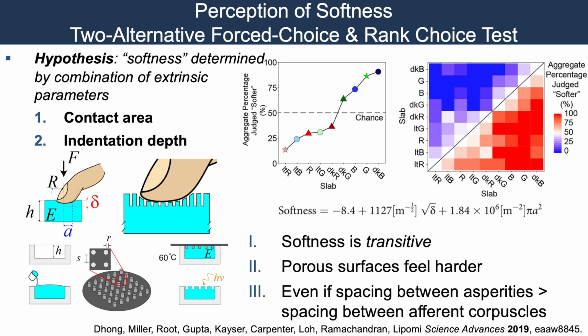So if you pour, in this case, just PDMS, silicone rubber, into a shallow well, it will feel hard even if it's soft, because it's very thin. So if you have a very thin, soft material, but you put it on a hard substrate, it's still going to feel hard because that material can't expand outward, and so the deformation is confined.